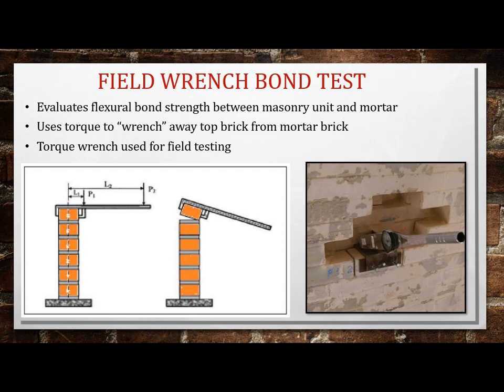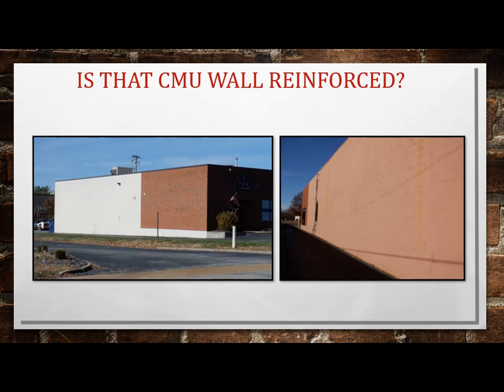So here's an example of the field wrench bond test. The picture on the right shows you remove enough block where you can clamp onto one brick, you cut out the head joint on both sides of it, you put a torque wrench on there, and you measure the force to wrench that top brick out. And that'll give you the flexural strength of that bond joint.